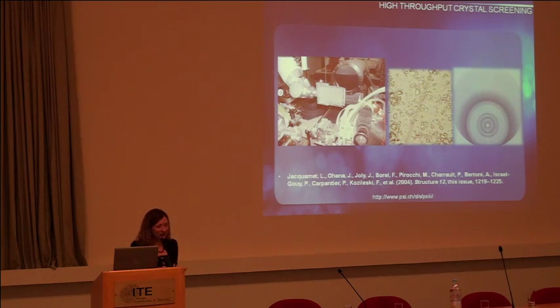For the high throughput crystal screening, many years ago in 2004, Jacquamet and co-workers for the first time at the ESRF, at the French crystallographic beamline, which is a single crystal beamline, put a crystallization tray. We crystallize our proteins in these trays, as you know. So they put this tray directly in front of an area detector using this robotic arm. The sample in each well looks like this in a successful crystallization experiment, and they could collect data which looked like this. By doing that, they could screen hundreds of crystallization plates in order to identify